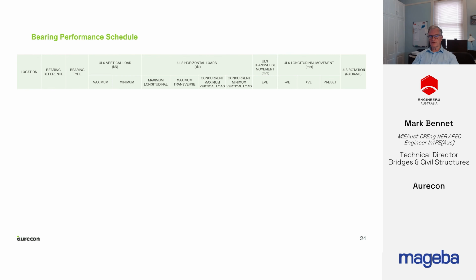Where uplift at ULS occurs, an additional column should be added to the schedule showing the minimum SLS vertical load on the bearing. To minimise the risk of construction errors, where the difference between the longitudinal expansion and contraction movements is less than, say, about 40 millimeters, it is recommended that the movement range be shown as plus or minus the largest movement to avoid the need for a preset. Where different load combinations result in significantly different concurrent maximum horizontal loads with minimum or maximum vertical loads for a single bearing, multiple load sets can be shown on the schedule for a single bearing.